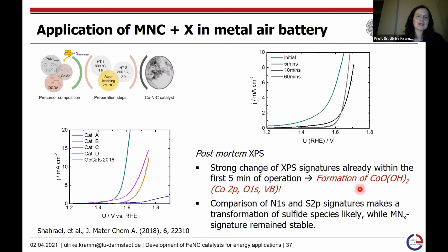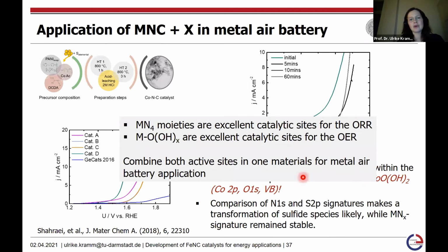But nonetheless, this gave the idea that, even if we might have some oxidic species, it is quite easy for this preparation, as if you do not perform any acid leaching, then you have side products that of course get oxidized. Based on that, you have a mixture of MN4 centers and some oxidic species. We thought this might be an easy way to prepare the catalyst, as you do not need to perform the acid leaching. And you can combine the benefits from the MN4 centers for the oxygen reduction reaction and the oxyhydroxide species for the oxygen evolution reaction, and then go for a bifunctional catalyst material for the metal air battery application.